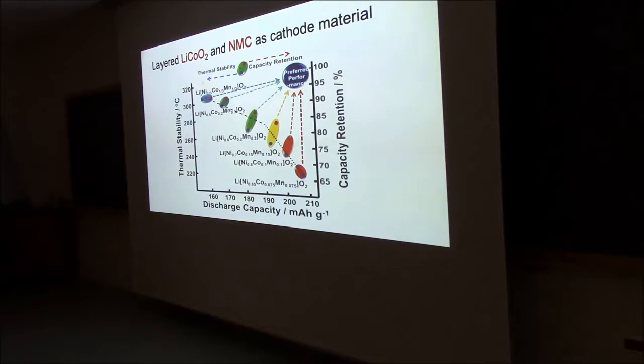So first here on the left, you can see the capacities are okay. The 3 elements, nickel, cobalt, and manganese, are 1 to 1 to 1. And what is interesting then, the capacity is okay, thermal stability is reasonably high. So you can see about 300 degrees, that's when something starts to get into trouble, to decompose. If you drop the cobalt, because that's interesting from a cost point of view, and you just go over there, you can see the capacity is increasing, the thermal stability is decreasing dramatically.